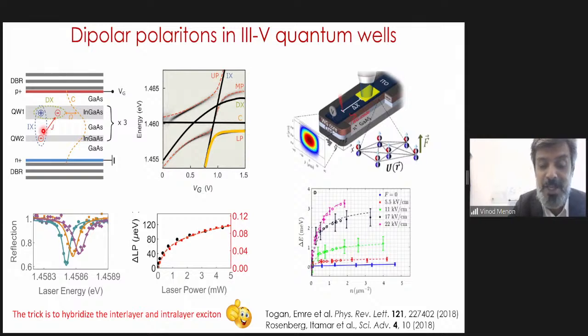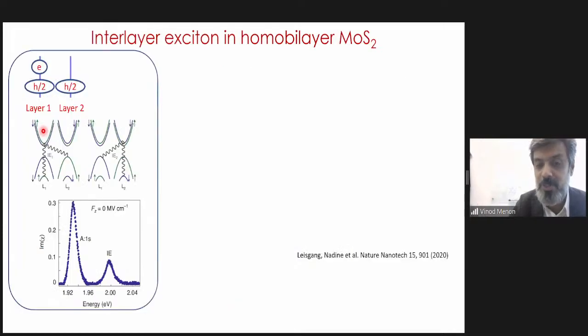So there was a lot of interest in these kind of dipolar polariton systems where you can get more interactions. And like I said, the goal here is to increase these interaction strengths so that you can actually go down to the single photon nonlinearities. Now, I just want to point out that with the work that we showed with Rydberg, the nonlinearities are such that we're still very much in the classical limit. You need about 200 photons to shift by one line width, or slightly more than that.